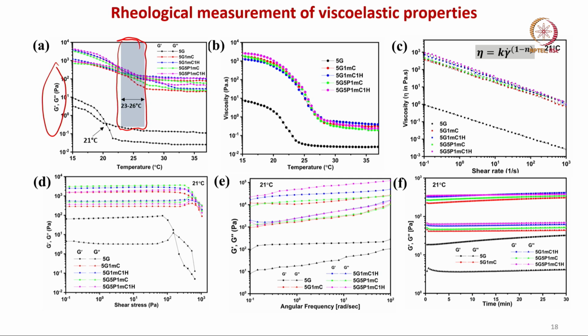And if you clearly see, with 5% gelatin the viscosity was very low, and viscosity is improved with the addition of carboxymethyl cellulose and hydroxyapatite, and also there are no significant differences among all the compositions, and it shows a qualitatively similar kind of trend with temperature.